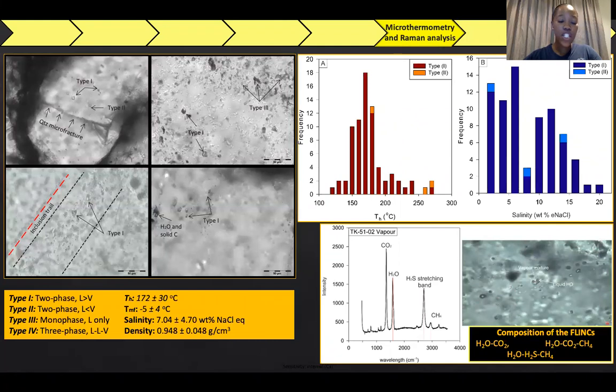The average homogenization temperature, or trapping temperature, is 172 degrees Celsius, and the average freezing point temperature is -5 degrees Celsius. The salinity was calculated to be 7.04 weight% sodium chloride equivalent, and the density was estimated to be 0.948 grams per cubic centimeter. Raman spectroscopy was also used to define the composition of the fluid inclusions, and the compositions observed were H2O-carbon dioxide, H2O-carbon dioxide-methane, H2O-hydrogen sulfide, and methane inclusions, and these are very important in the later sections.